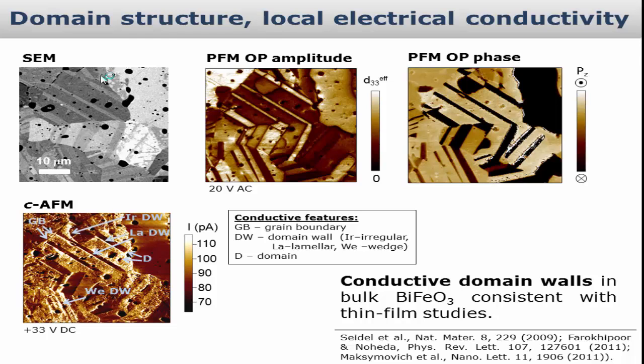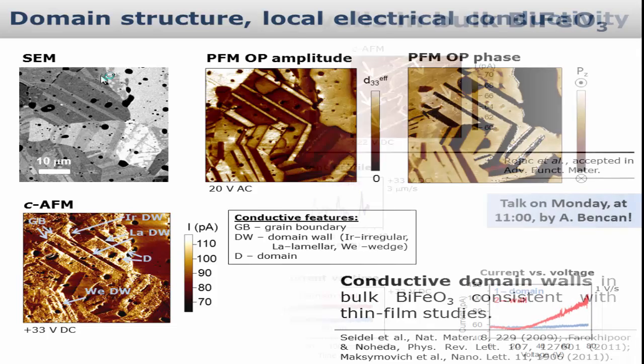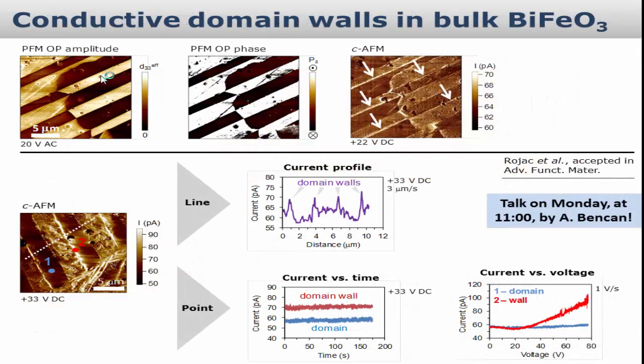So we take an AFM tip, travel around, apply a constant DC voltage, and measure current. Whenever we cross a domain wall, we saw a spike in current, which looks like there is some conductivity at these interfaces. We check this then with various other ways within AFM.